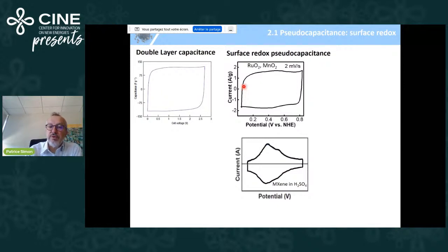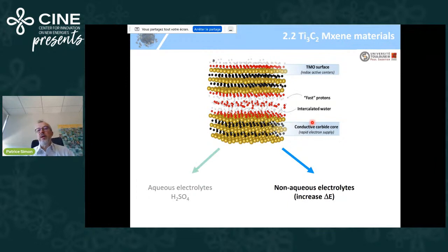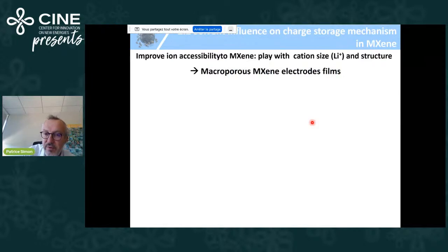But anyway, first, what you see is that by using these MXenes in sulfuric acid, you can now prepare a second kind of surface redox pseudocapacitive materials with this very nice cyclic voltammetry. But the key now is to try to make these MXenes operate in non-aqueous electrolyte to increase the delta E, the potential window, and then the performance, I would say. So we failed for years, but I'm going to show you two examples of results we got, which are really promising and say that, yes, we can make it, and it may have an interesting impact on the high-power battery community.